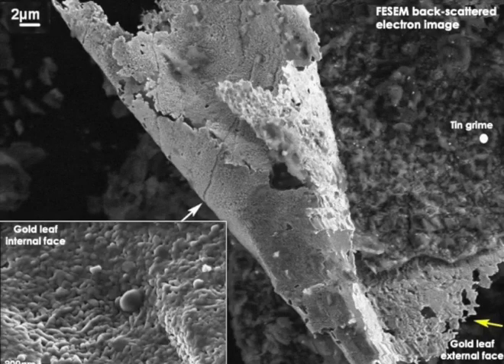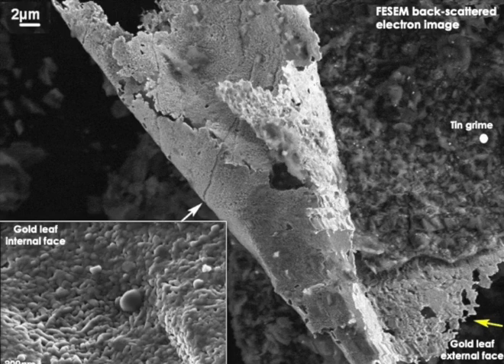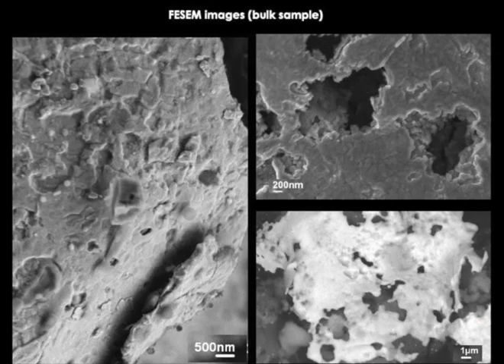The galvanic corrosion process explains neither the weathering of the gold leaf nor the gold nanoparticle formation. Note in this image that the two gold faces show different textural features. The inner face shows a cobble-like structure made of tabular crystals encircled by nanoscale channels. In contrast, the smooth outer face has abundant nano and micro-sized pits. Larger pits result from coalescence of smaller ones, yielding micro flakes.